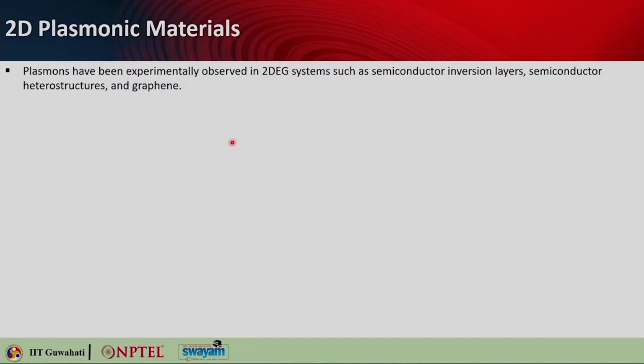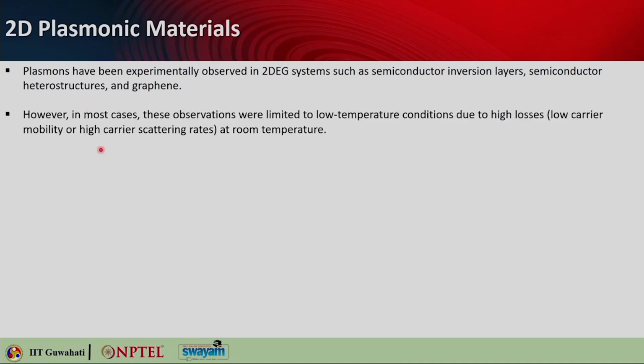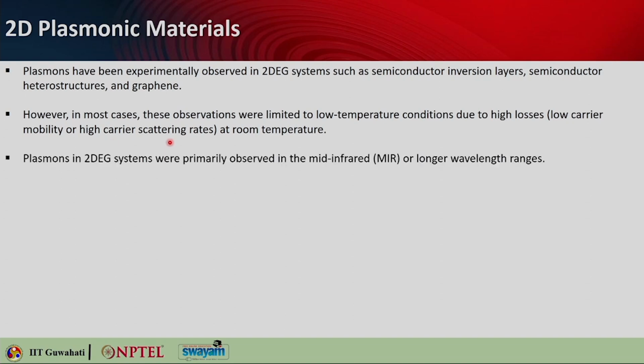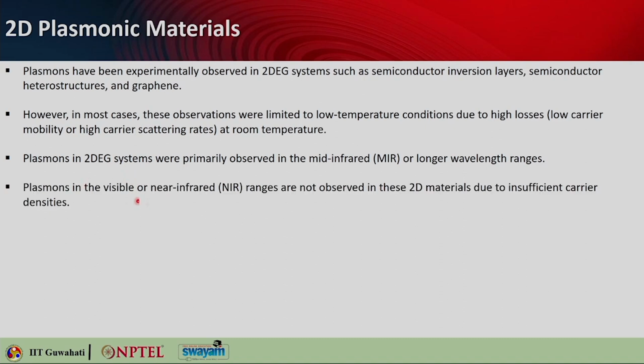Now, plasmons have been experimentally observed in these 2D electron gas systems such as semiconductor inversion layer, semiconductor heterostructure and graphene. However, in most cases these observations are limited to low temperature conditions due to high losses, and here the high loss is because of the low carrier mobility or high carrier scattering rate at room temperature. If you think of plasmons in 2D electron gas systems, they are primarily observed in mid infrared or longer wavelength range. So, plasmons in visible and NIR are not observed using these 2D plasmonic materials due to insufficient carrier densities.